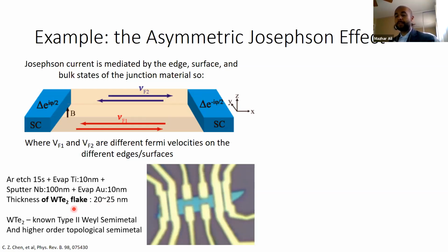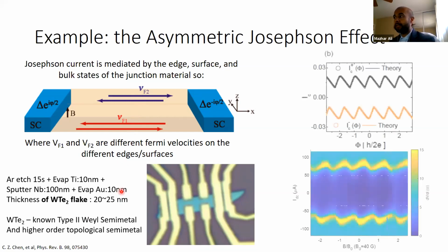It is an inversion symmetry breaking topological semimetal. It was known as maybe the first type 2 Weyl semimetal. Nowadays, it's known also as a higher order topological semimetal. It does everything. Somebody's talking about it as an excitonic insulator now, what have you. The point is, it breaks inversion symmetry and it has these localized conducting states. And pretty much as the theory expected, you can end up with a modulation to the Josephson effect, particularly that sinusoidal relationship isn't sinusoidal. It ends up being more like a sawtooth in the current versus phase, and that's pretty close to what was observed.